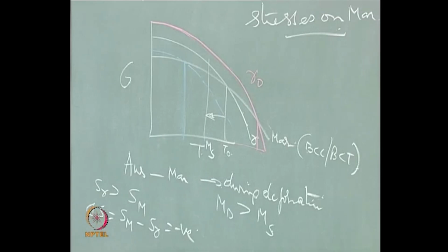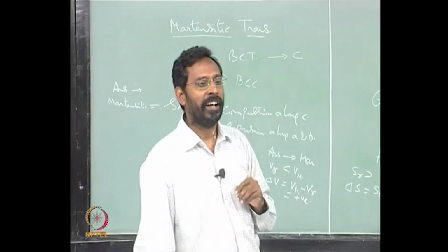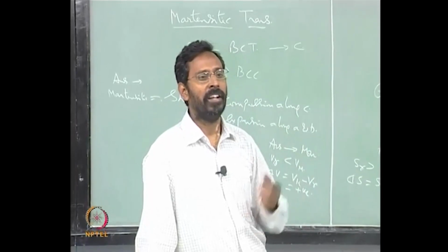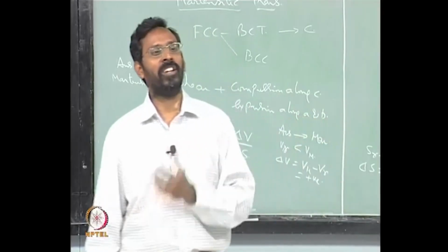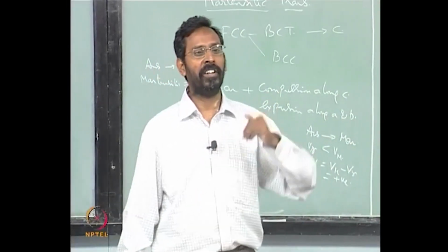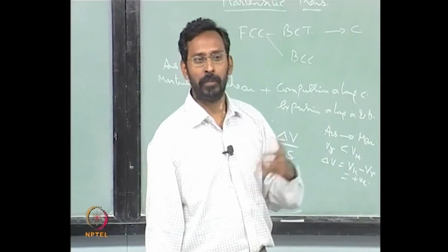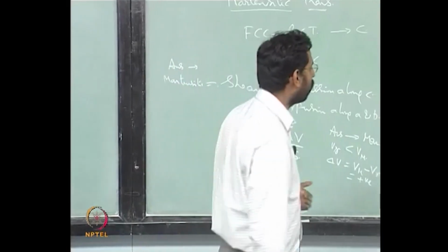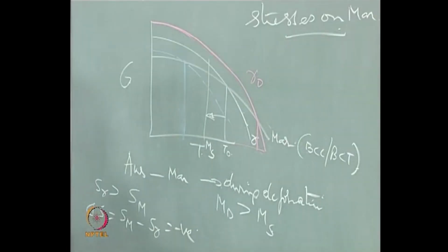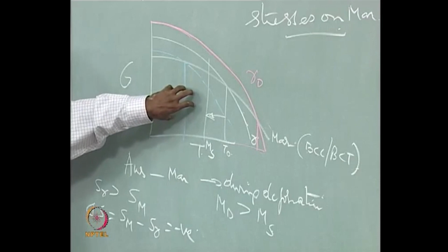So in case you take iron or steel powders in the gamma state and then do hipping and then quench it, and you compare it with another steel produced by the normal route, you would see that the martensite transformation occurs at a much lower temperature when compared to a normal steel. Only in such a case can you actually confirm that, and in normal steels we do not need to use hipping at all. So this is of more concern for powder metallurgy people.